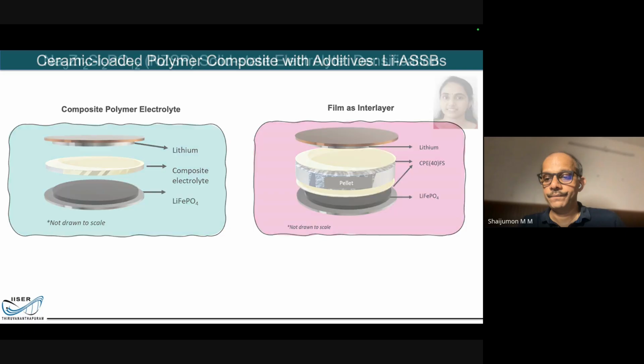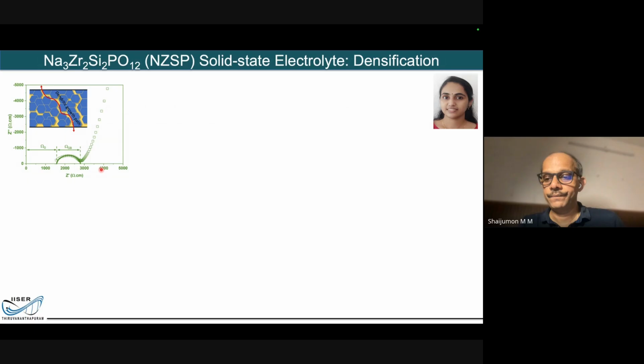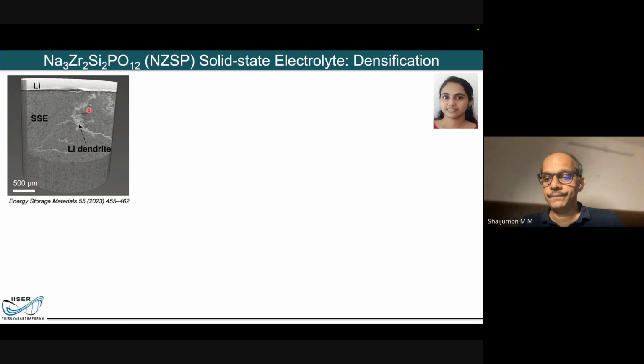So these are some of the directions that are happening, right? I mentioned the densification of this electrolyte. The reason is very simple, because think about it. This is a tomography picture wherein you see the lithium electrode, which is the anode, and you have a cathode here, and this is the solid state electrolyte, right? Supposedly it should be a very solid compartment, but what happens is you see these white lines appearing. These are basically the lithium dendrites. I said there will be dendrites, needle-like structures, right? This is so solid, and still it finds its way towards the cathode, because this material is not very densely packed. So it finds its way through the gap, and the lithium penetrates like this. And finally, it will touch the cathode and short.